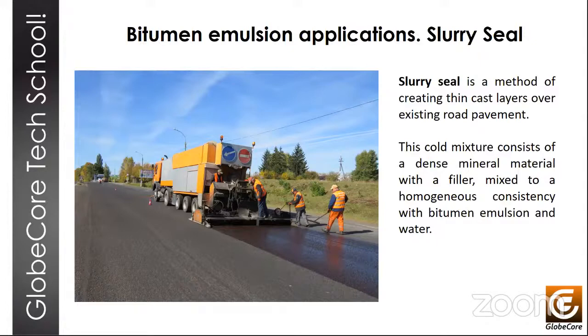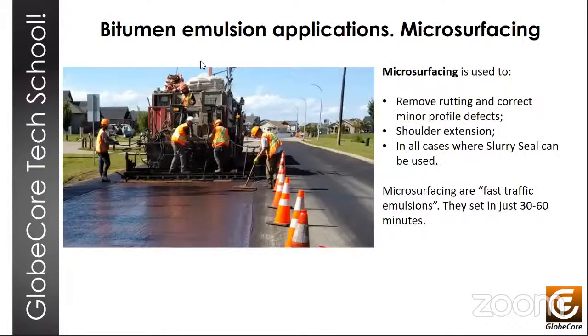Microsurfacing is used to eliminate rutting, fix minor profile defects, and expand road shoulders. In any case where slurry seal can be used, microsurface can be used as well. Microsurfacing emulsions are fast-setting, setting in just 30 to 60 minutes. If the coat is created in 2 passes, the first layer closes cracks and smooths out the surface, and the second coat is recommended to be applied no earlier than 1 day later.